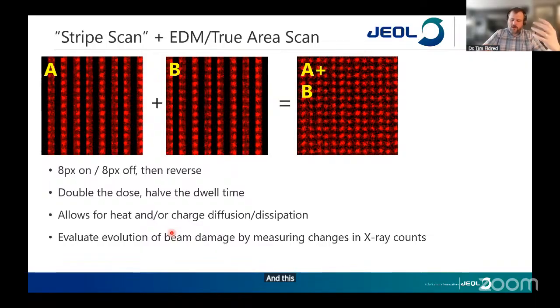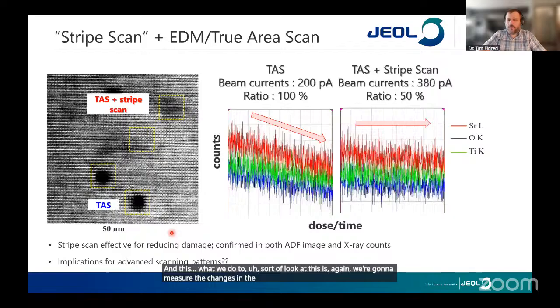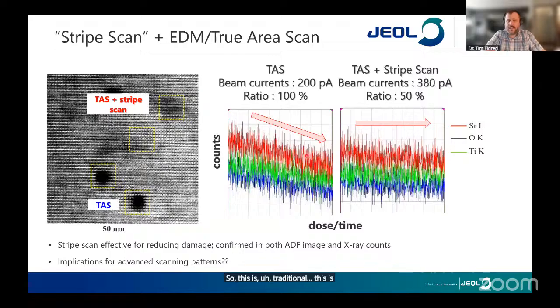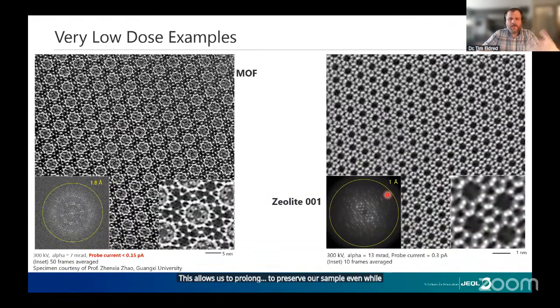And what we do to look at this is, again, we're going to measure the changes in the X-ray count over time. So this is traditional. This is our best case with the true area scan where we're cutting it off on the way back. If we apply that and this striping pattern, suddenly what was a very slow decrease is now an almost imperceptible decrease in some of the elements. This allows us to preserve our sample even while dosing.